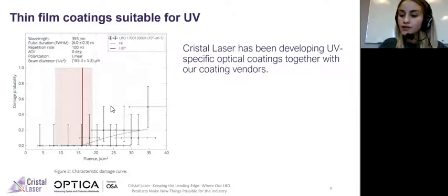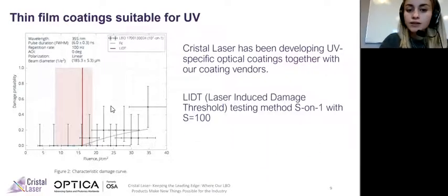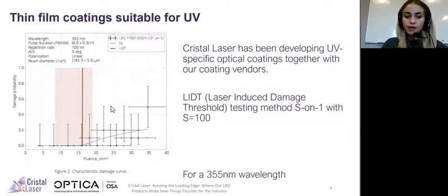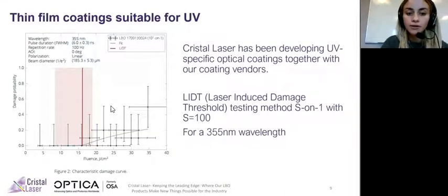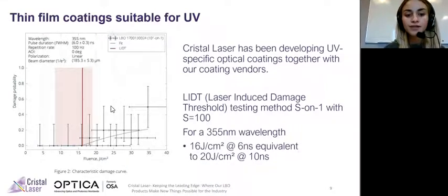On this slide, you can find the damage curve for LBO, which was coated with this specific design with a double bond coating. This is a test to measure the laser-induced damage threshold, also called LIDT. The method used to test the LIDT here was a method called S-on-1 with S equals 100. The wavelength used here was 355 nanometers, so in the UV region. And the result we got was 16 joule per centimeter square at 6 nanoseconds, which is equivalent to 20 joule per centimeter square at 10 nanoseconds.